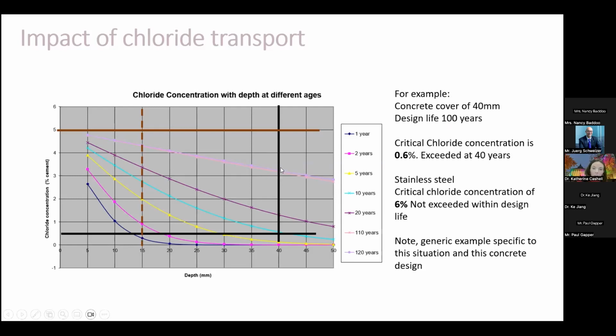On the other hand, if we move further up the y-axis, stainless steel rebar, which has a critical chloride concentration value of 6%, is not met at any point in the design life. So this is quite a generic example, and it is specific to this situation, but it shows how resistant and resilient stainless steel reinforcement is to chloride penetration, and how that can extend the design life of structures.